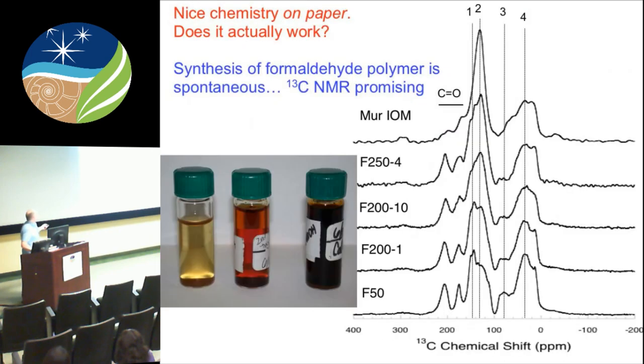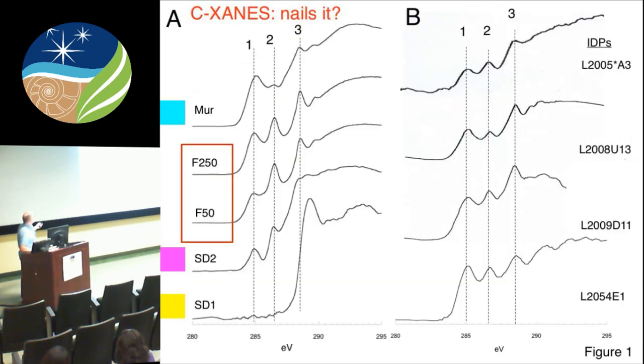And you could argue, does C-XANES nail it? I think it does a pretty good job. So here are two stardust particles. This is what I call the very primitive stardust particle. It's essentially pure polyalcohol. This is, I would say, a more evolved stardust particle, so it has some ene carbon, some keto carbon. These are two of the formaldehyde polymers that are now evolved away from formaldehyde, these black solids. They have the same three peaks that this one has. This is Murchison, 1, 2, 3 peaks.